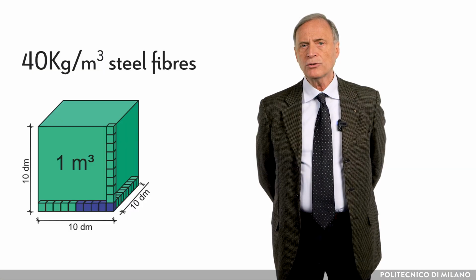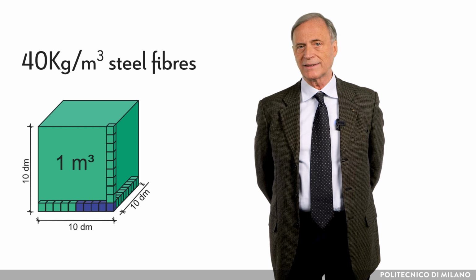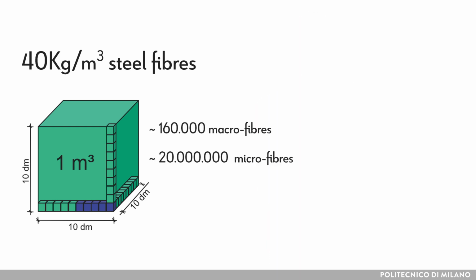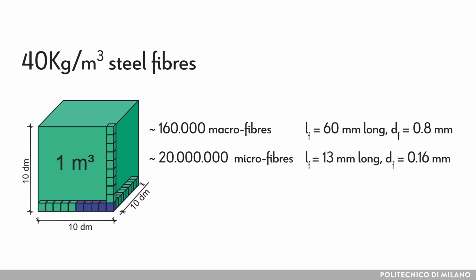The strengths characterizing the three steel classes are aligned to the values of conventional rebars, drawn wire bars, and steel used for pre- or post-tensioning. Looking at the most used steel fibers, the structural effectiveness is guaranteed only if fibers are well dispersed in the volume. If fibers are concentrated, no local toughness is achieved. Obviously, for example, an amount of 40 kilograms of fiber in a cubic meter of concrete corresponds to a growing number of fibers depending on fiber sizes. We can count around 160,000 fibers up to a total number of around 20 million, passing from macrofibers 60 mm long with a diameter of 0.8 mm to microfibers 13 mm long with a diameter of only 0.16 mm.